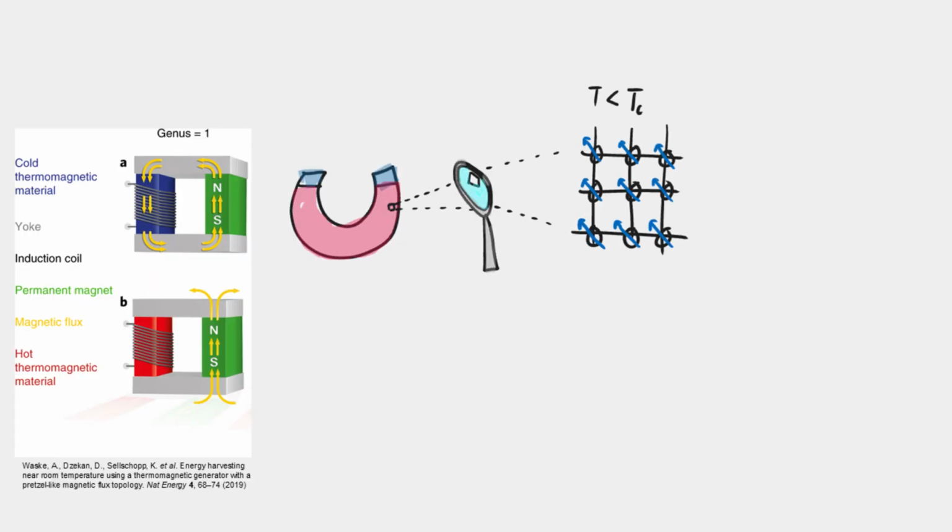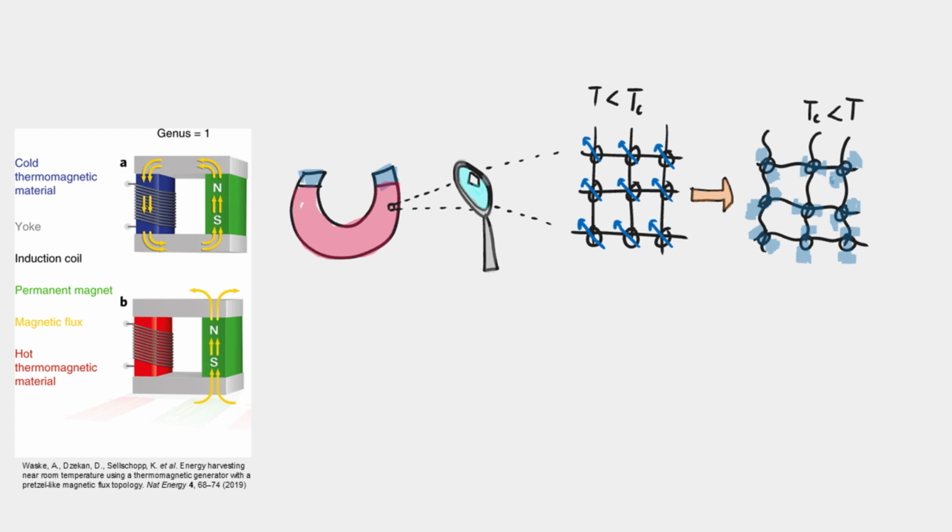The bulk magnetization of a material is a result of the many small contributions from the structure of electrons within. When the temperature of magnetic material is below a critical temperature, there is not too much motion in the electronic structure, and the material can be in a magnetically ordered state, where the many small contributions from the electrons add up to a relatively big bulk magnetization. When the temperature exceeds the critical temperature, the motion in the structure can cause the material to be in a magnetic disordered state, where the many small magnetic contributions are scrambled in a way that does not simply add up.